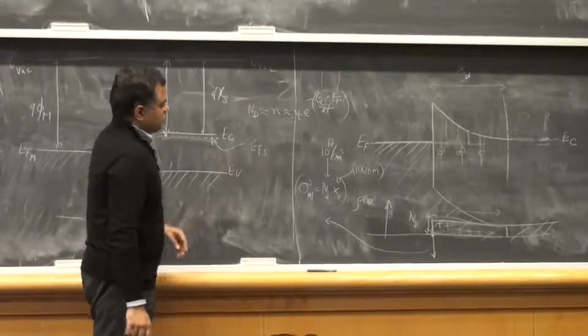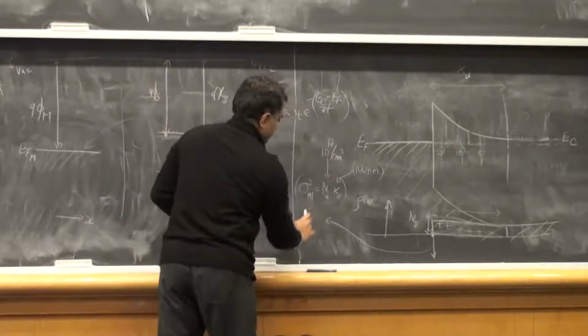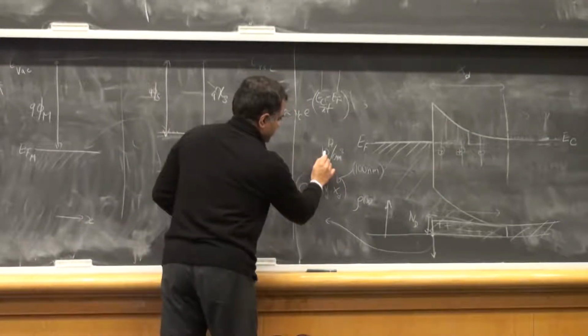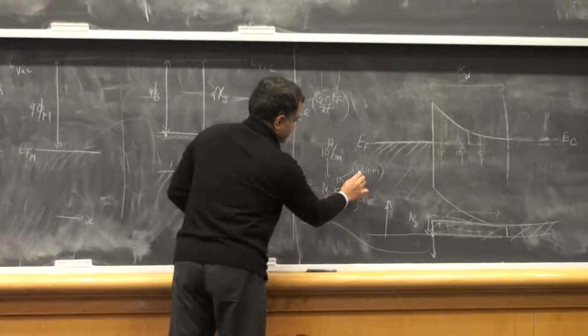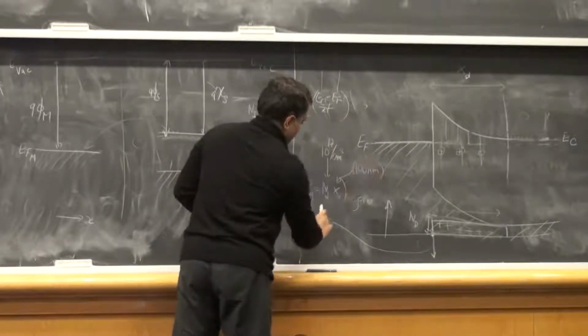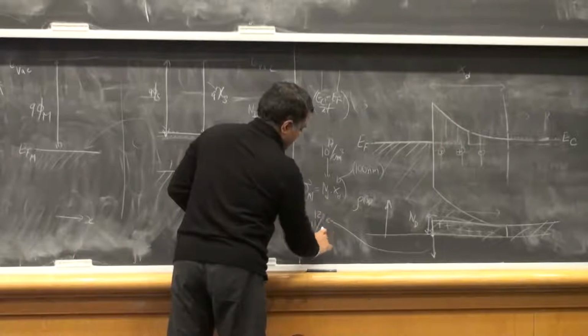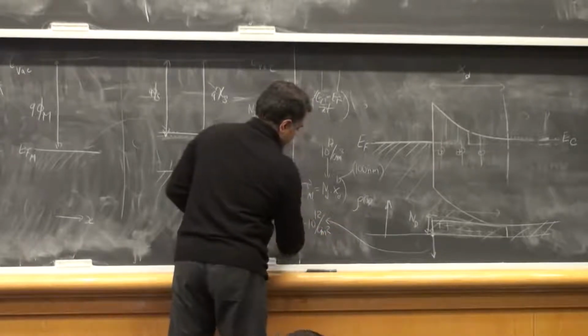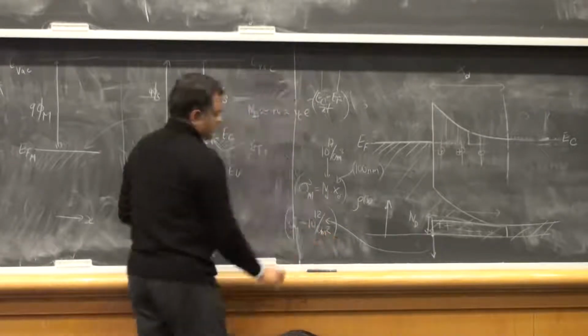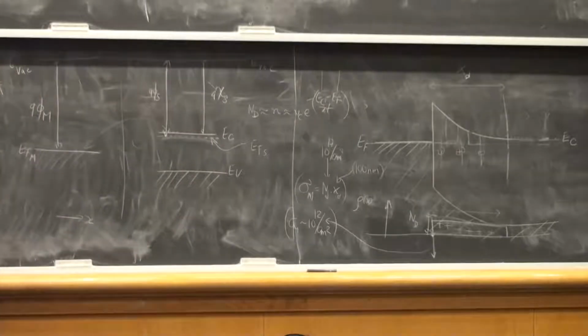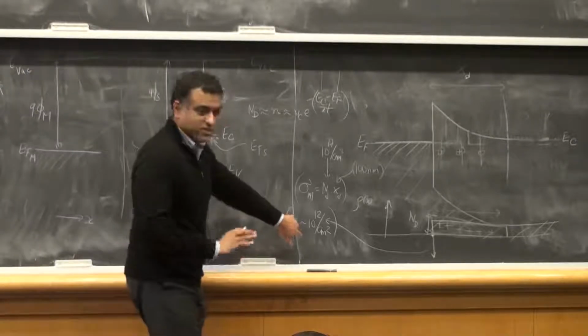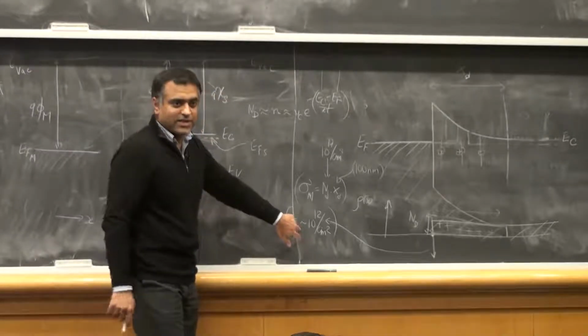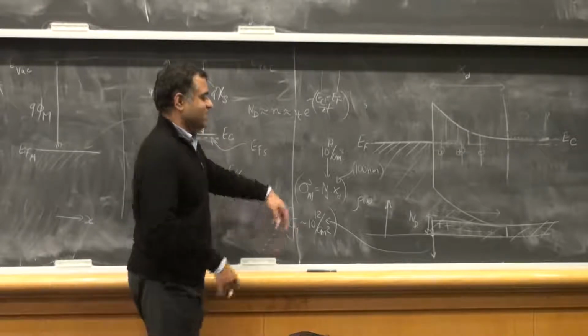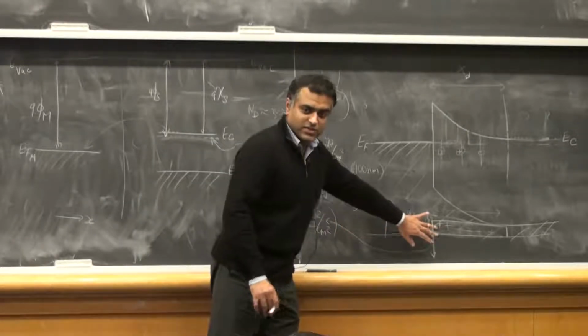And so when you multiply the two, you get 10 to the power 17. 100 nanometers is 10 to the power minus 5 centimeters, so you get about 10 to the power 12 per centimeter squared, which is the sheet density of charges. This is, give or take, the sheet density at pretty much every heterojunction you can ever encounter, metal-semiconductor or semiconductor junction. The order of magnitude of sheet density is about 10 to the power 12, on a silicon MOSFET. So this is roughly the order of magnitude.